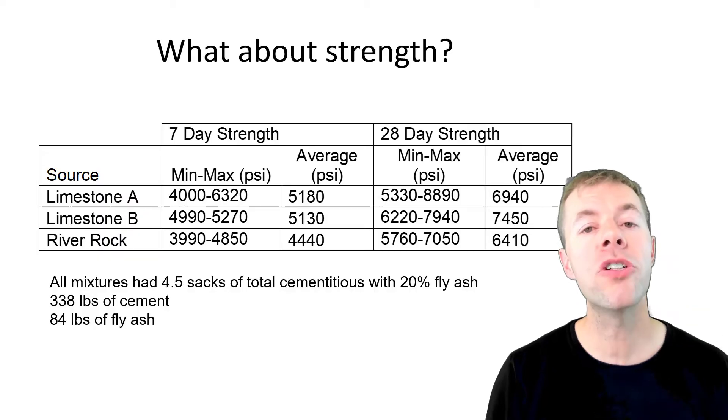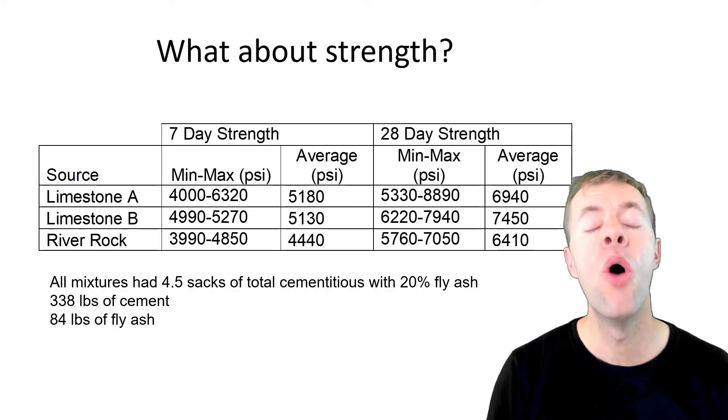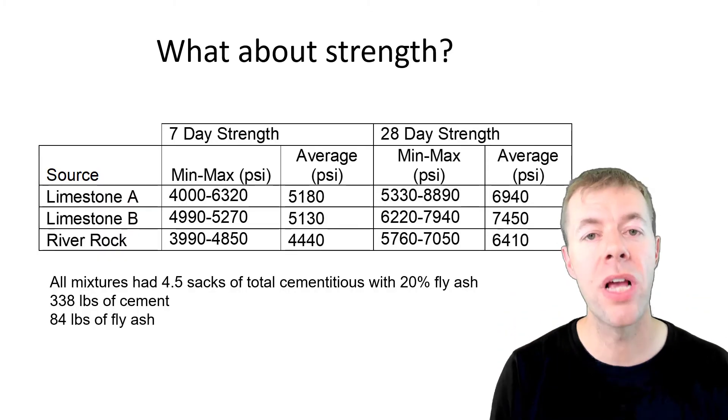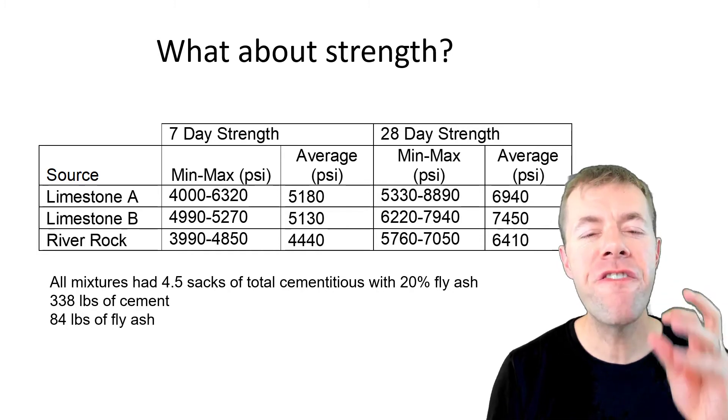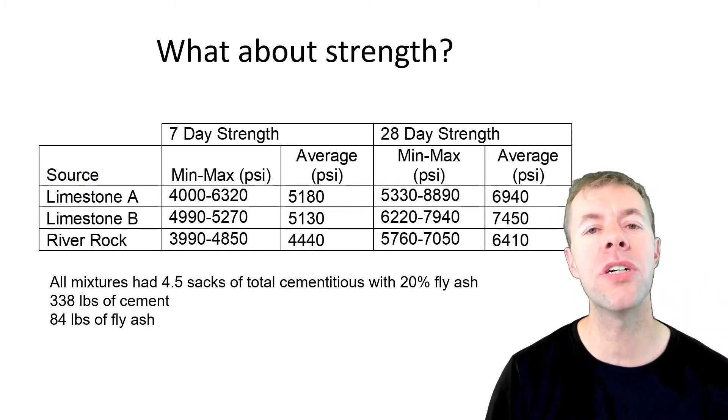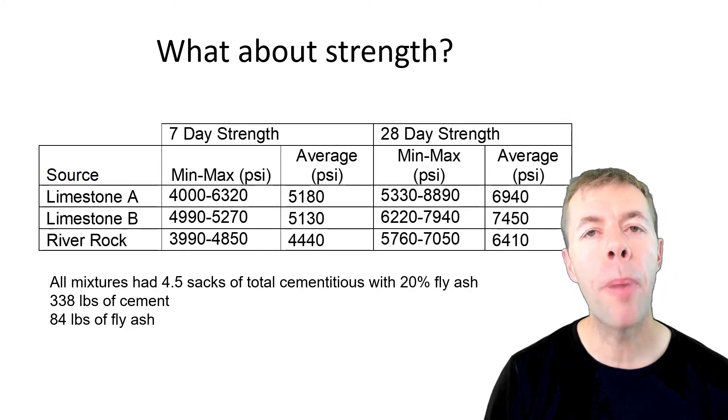What about strength? I have done tons and tons of experiments. Strength does not have a lot to do with aggregate — some, but not a lot. It's mainly about water-to-cement ratio, at least in the strength ranges that we're typically interested in. I'm showing some examples here — lots of data where we can get great strengths at seven days with very low cementitious content, very low binder content.